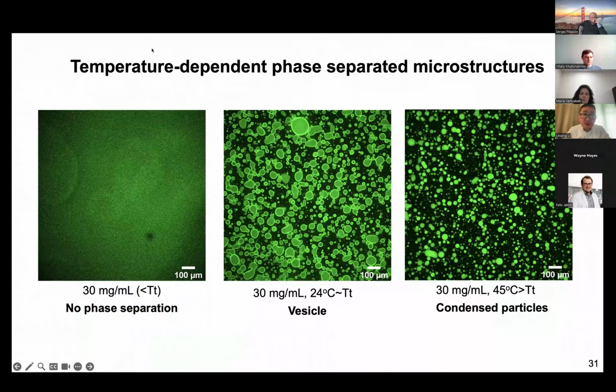It is also interesting for us to know that these hydrogels have autofluorescence properties, which is great for us to actually observe so that we don't need to label the domains. So again, this is the hydrogel below the transition temperature. You can see there's no defined structures. And interestingly, when we form the hydrogels close to the transition temperature, instead of getting particles, we have these vesicle formations in the system,